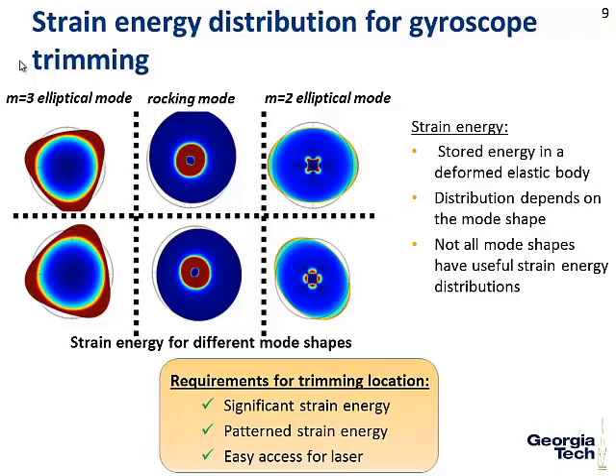But what you can also observe is that the strain energy pattern for the high frequency and the low frequency mode is actually very similar. So if you do any modification for this mode, you're going to do the same modification for this one. So if you have strain energy, but they have the same pattern for the high frequency and the low frequency, so for the drive mode and the sense mode, then in that case, you're not reducing the frequency split. What you're really doing is shifting both modes without ever changing the frequency split.